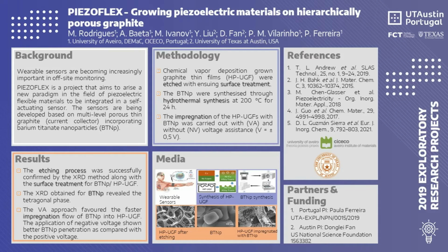The current passing through the foam was measured while the impregnation was occurring with a steady voltage of 0.5 volts to qualify the impregnation flow. The higher the current, the deeper the particles reached.